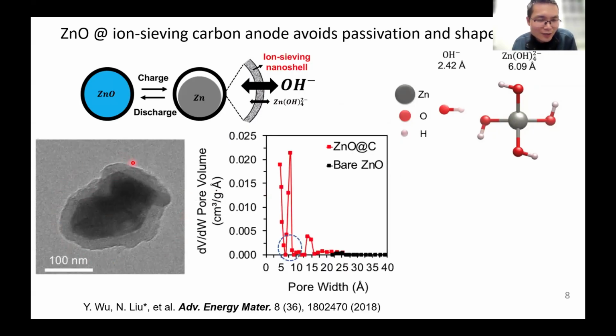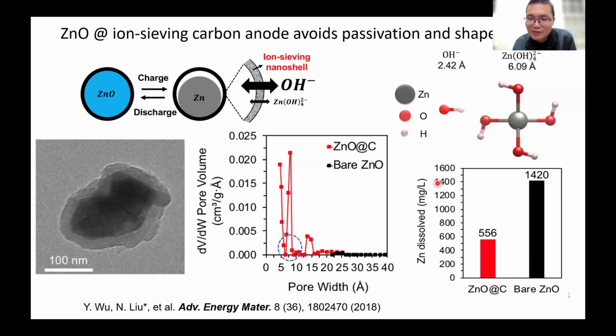This is how the material looks after synthesis. You can see the zinc oxide in the middle and the carbon outside. We did pore size analysis on the carbon, and we find the pore size is indeed between the hydrated ion sizes of these two ions. We put the particles in the KOH electrolyte to see if the coating can indeed confine and slow down the dissolution of the zinc oxide inside. We measured the concentration of zinc in the liquid solution, and we find that with the carbon coating, the dissolved zinc is much less than with the bare zinc oxide particle.